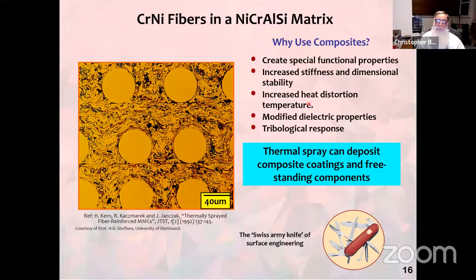So here's an example, very old, 1992, from University of Dortmund by Professor H.D. Steffens, one of the early workers. His thesis came out decades ago. But what he was able to do with his group was get the chrome nickel fibers that you can see embedded within a nickel chrome aluminium silicon matrix to get a composite with special functional properties: stiffness, dimensional stability, resistance to heat distortion, dielectric properties, etc.